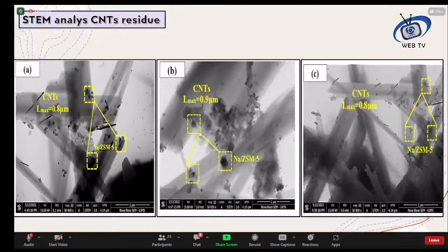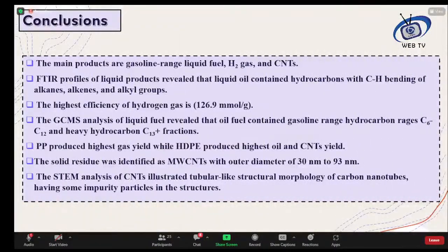In the PP case, we see that the solid residue was small, but the impurity was also small as compared to case one, and the impurity level reduced further, and the structure of the carbon nanotubes improved when we mix these two. It shows that when we mix two feedstocks, the hydrogen production remains almost the same, but the amount of carbon nanotubes decreases over time, and quality improves with time. So here are some conclusions of our work.